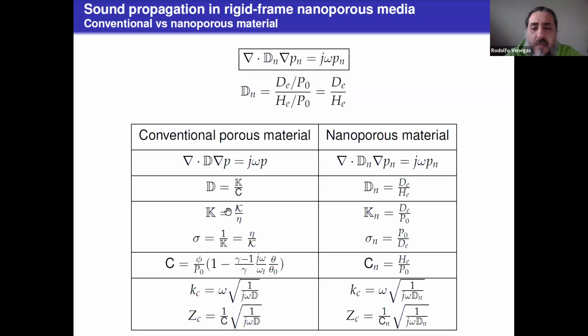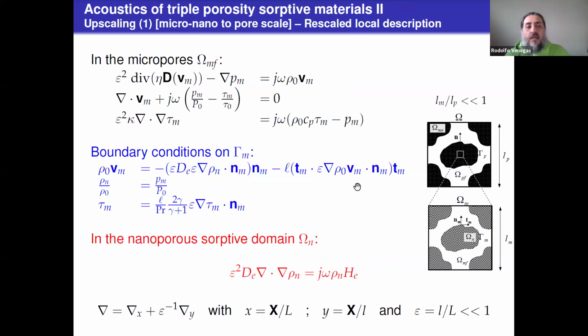If we compare these two equations, they are formally the same, and we can define the pressure diffusivity in a conventional porous material as the ratio between the hydraulic conductivity and compressibility, and in a nanoporous material, the ratio between these two parameters. And the other expressions show the direct parallel between these two types of medium.